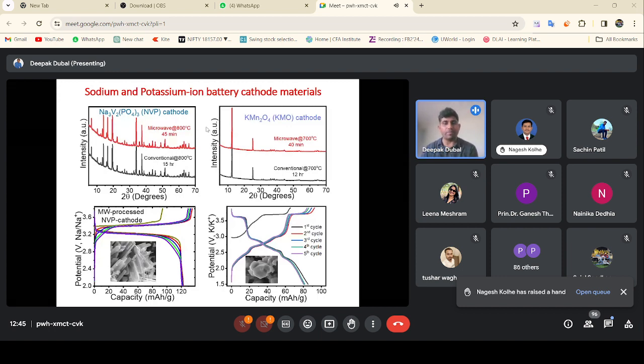The most highlighting part of this microwave synthesis is, you can see here the charge-discharge curve. All these electrochemical signatures are very, very strong. So it means all the components in this material are electrochemically active, and that is the reason that in the charge-discharge curve, and at the same time in cyclic voltammetry, we can clearly see the oxidation and reduction peaks for each of these materials. And that is one of the reasons our hypothesis is that the material formed using microwave synthesis is extremely pure, has fewer defects, and is of really very high quality. So this is most of the results which we have generated.